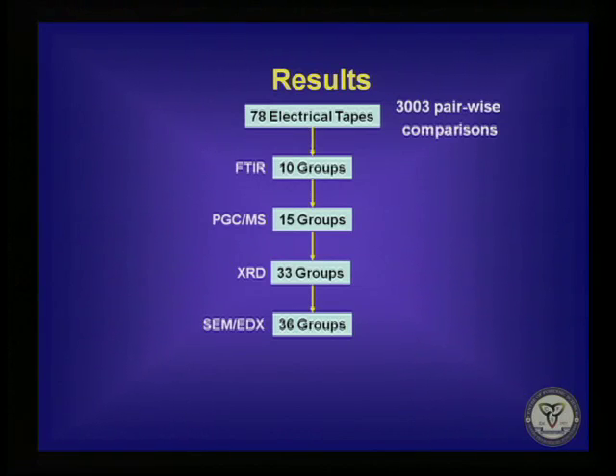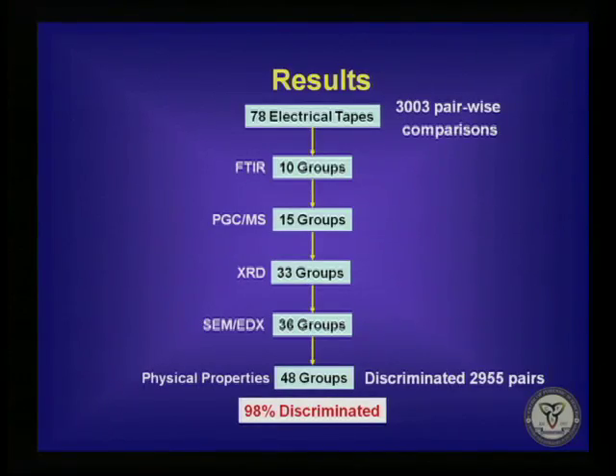So that's for the chemical composition. And then lastly, we looked at the physical properties, microscopy, thickness and width, and we were able to further separate those 36 groups into 48 groups. So in our overall results, we were able to discriminate 2,955 of the 3,003 pairs, which gives us a 98% discrimination.